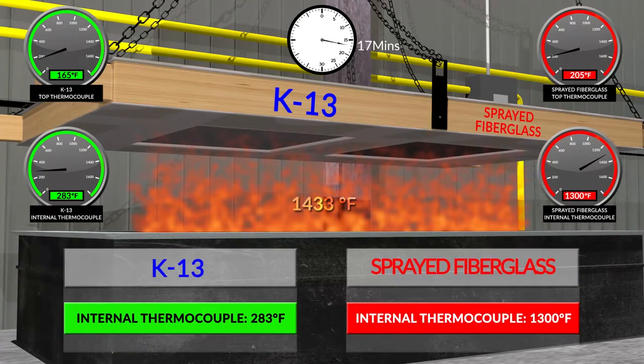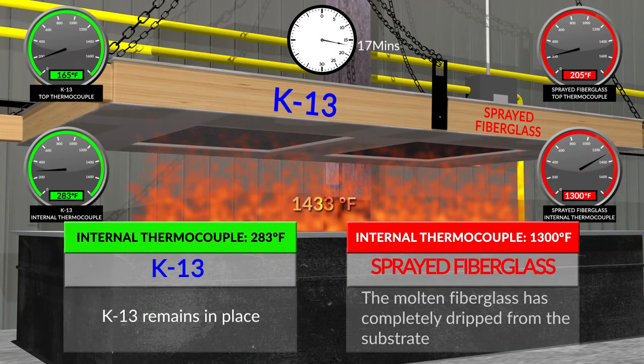At 17 minutes, K-13, internal thermocouple is 283 Fahrenheit. Sprayed fiberglass, internal thermocouple is 1,300 Fahrenheit. K-13 remains in place. The molten fiberglass has completely dripped from the substrate.